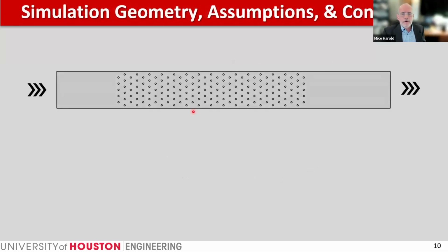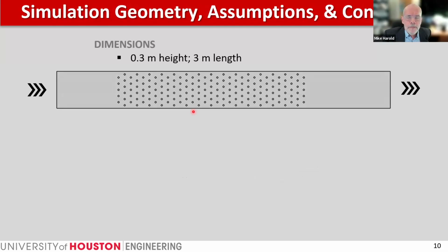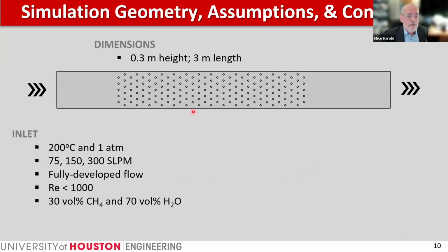wires, I should say. Now, our envisioned reactor is shown here schematically. So we have flow from left to right. These are all rods in this case. Here's our inlet conditions, and I'm just showing you some results of some simulations with these conditions in mind. So a 30% methane, 70% steam with these conditions coming in, preheated, atmospheric pressure, fully developed flow, and here's the volumetric flow rate.